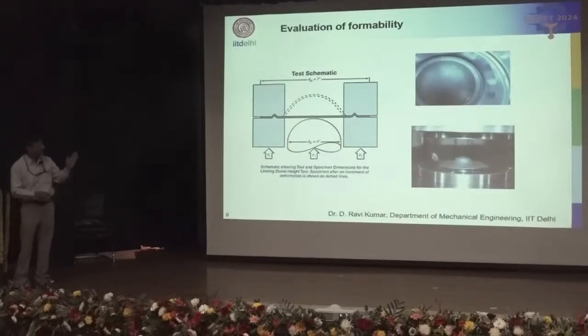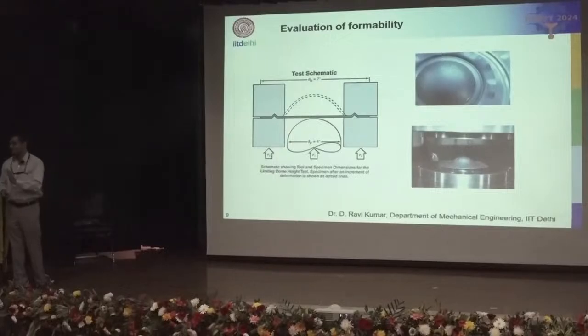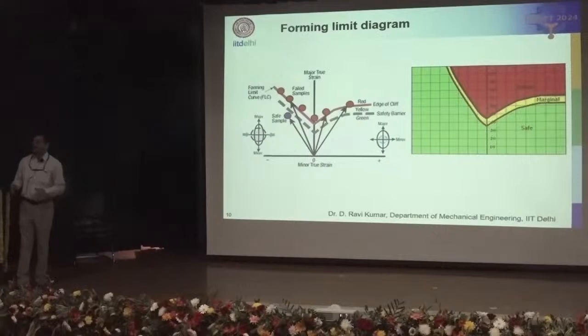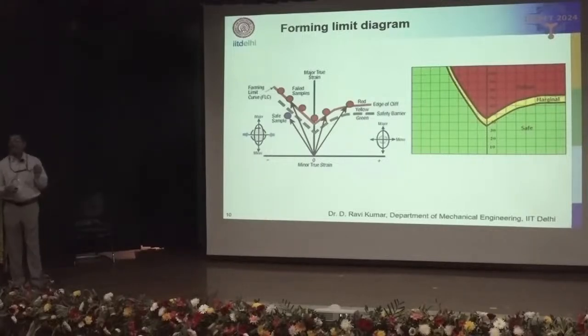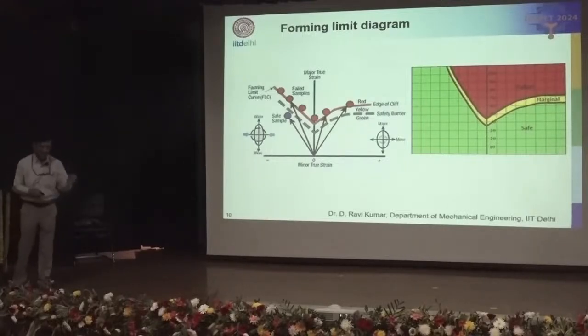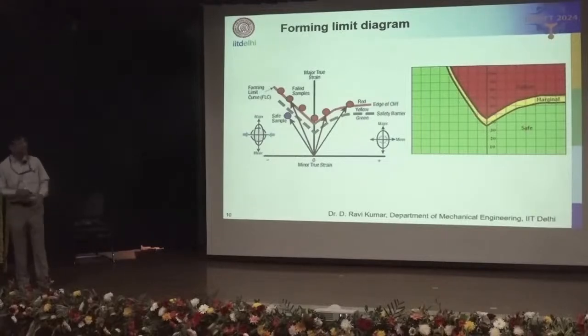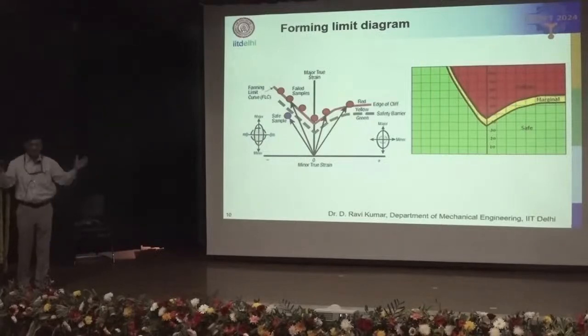In every test, the mode of deformation is the same. So every test will give you formability of a material in one particular mode of deformation. But suppose I want the limit strains of a sheet metal in all the possible modes of deformation, then we evaluate a diagram called forming limit diagram or a forming limit curve. As you can see, this is a plot between major principal strain and minor principal strain measured on the surface of a sheet after deformation.